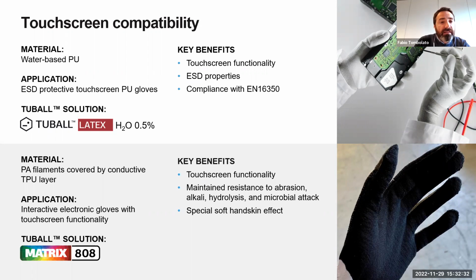Different application, interactive electronic gloves with touchscreen functionality. In this specific case, the yarn itself was modified to achieve the electrical properties. Polyamide filaments were covered with thermoplastic polyurethane made conductive using Tuball Matrix 808 to achieve touchscreen functionality, but maintaining the mechanical and the chemical resistance of the material.